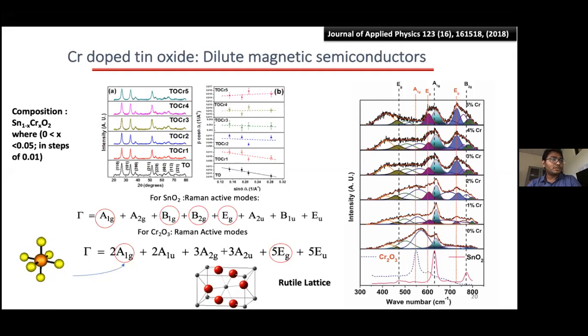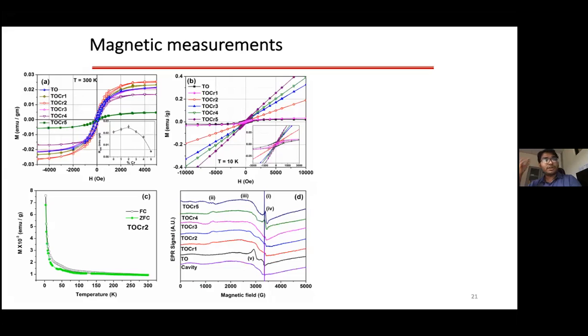So that's how we looked into that, and the electron paramagnetic resonance further confirmed that the signal due to the oxygen vacancy, which we had ascribed, went on increasing with more and more chromium doping. So that further strengthened the claim. But then there was a catch: if you go on doping something in the crystal, there's a limit to which it can digest. After that, it will start throwing it up into interstitial sites, or it will start phase segregating out. So that is called the solubility limit.